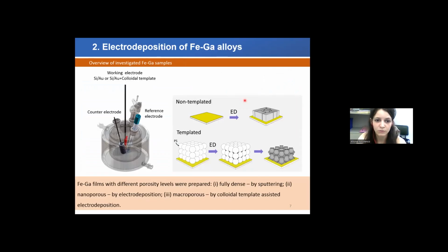So in this work, we were preparing iron gallium alloys by electrodeposition, and we employed a standard 3-electrode cell. However, the working electrode in one case was just a flat, not patterned silicon substrate metallized with gold for conductivity, and the films were directly grown on the substrate. In the other case, to induce a high degree of porosity in the films, at the initial step we deposited some polystyrene spheres using electrophoretic deposition on these silicon gold chips, and then this patterned substrate was used as a working electrode.